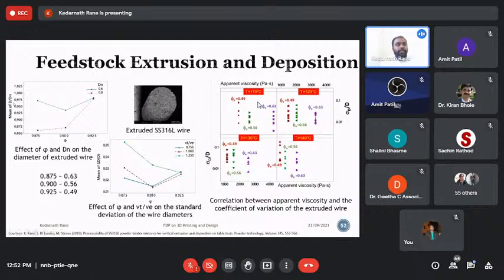0.925 is so, it means that different swelling ratios are employed to correct the deposition. Why we did all this study is to make sure that whatever we are controlling on the computer is getting deposited, because there is expansion of the material because of the feedstock constituent polymers.